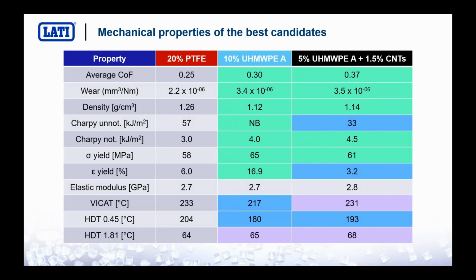So these are, in our opinion, the best candidates that we obtained, in the second and in the third column. The first one in the second column was the material with 10% of type A ultra-high molecular weight polyethylene. And the other one is 5% of ultra-high molecular weight polyethylene plus the carbon nanotubes to improve the wear resistance. But as you can see, we have already tested this material from other points of view.